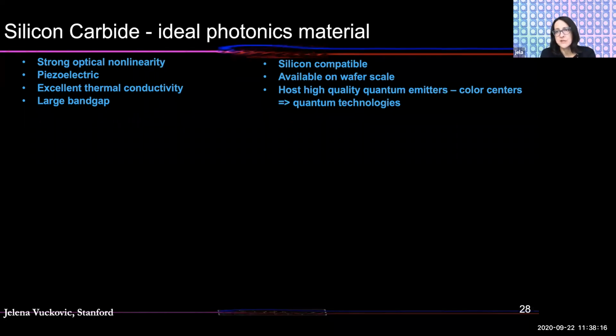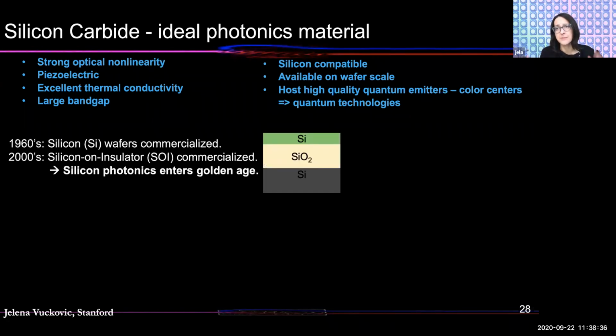You pretty much use the same process to make structures in silicon carbide and in silicon, same chemistry, same etching. It has excellent thermal conductivity, large band gap, but also it has a strong optical nonlinearity, both second and third order, and it's also piezoelectric. And there is no other material that actually covers all of this, that exhibits all of these properties at the same time.